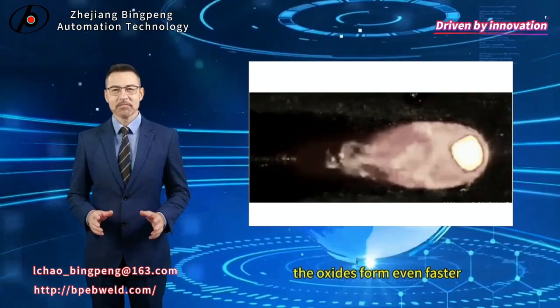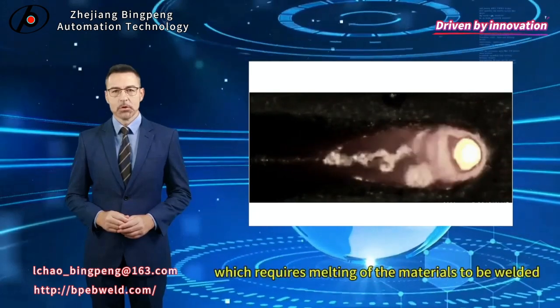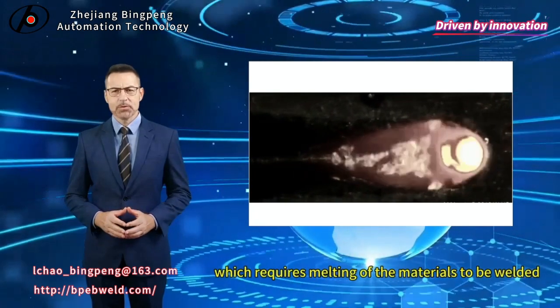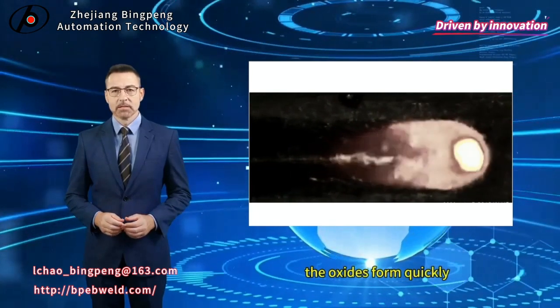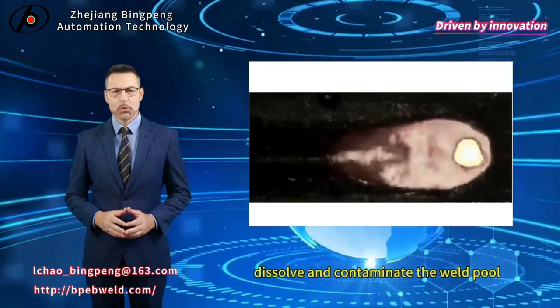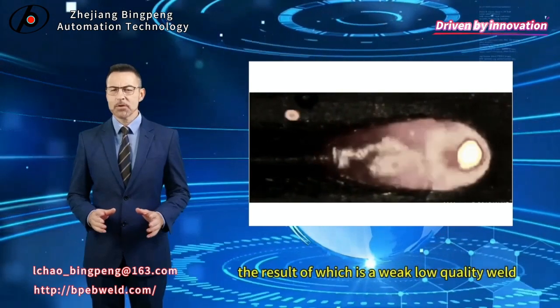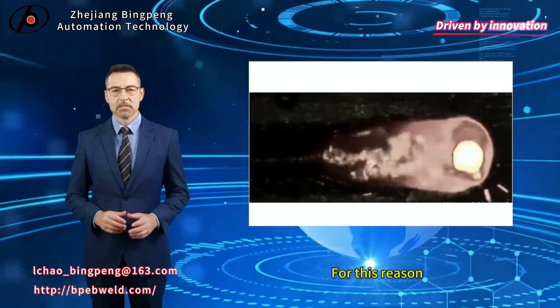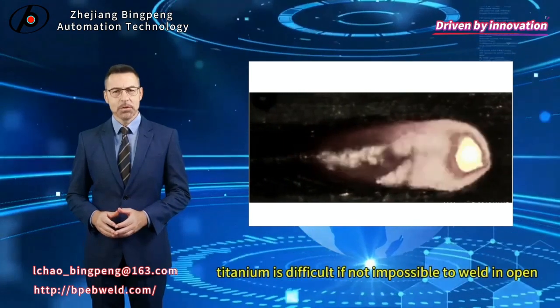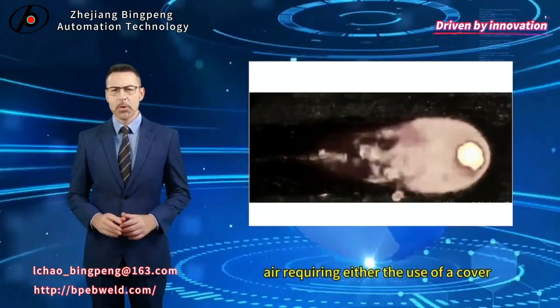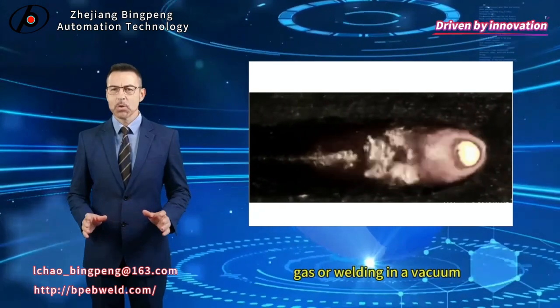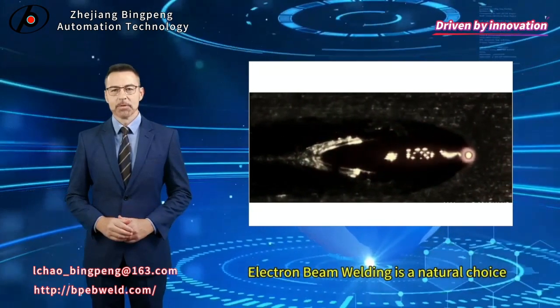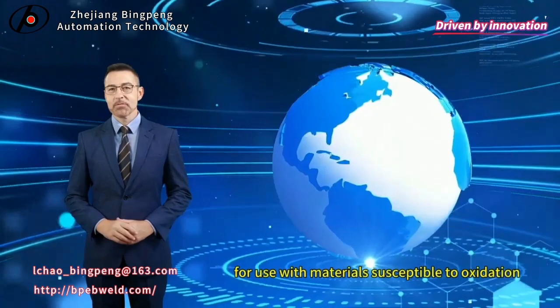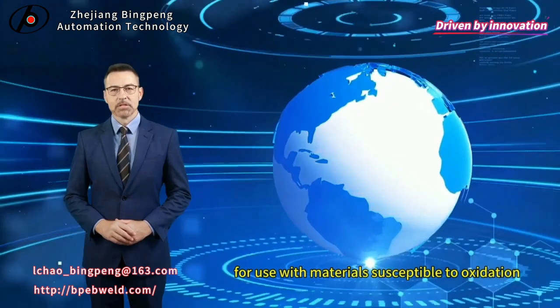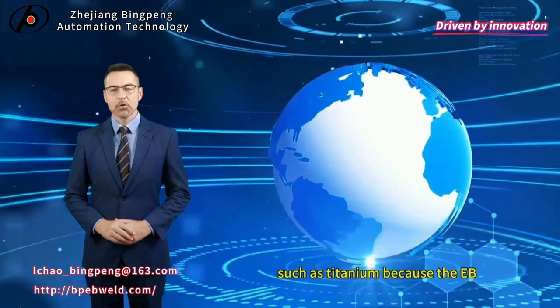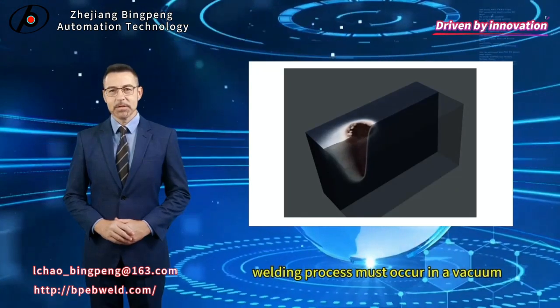The oxides form even faster during welding, which requires melting of the materials to be welded. The oxides form quickly, dissolve, and contaminate the weld pool, the result of which is a weak, low-quality weld. For this reason, titanium is difficult if not impossible to weld in open air, requiring either the use of a cover gas or welding in a vacuum. Electron beam welding is a natural choice for use with materials susceptible to oxidation, such as titanium, because the welding process must occur in a vacuum.